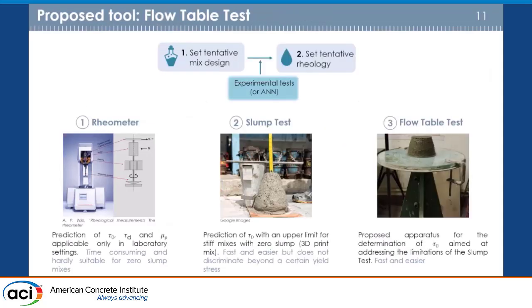So where did we start? We started with a tentative mix design and a tentative rheology, and tried to use that as feedback back and forth for an artificial neural network. But when we went into the rheology, the issue, as I said before, was how do we measure it? With most of the commercially available rheometers, it's quite difficult. So we went back to the flow table test, which seemed quite reliable and effective, also if you want to do it on a job site in order to control the rheology of your